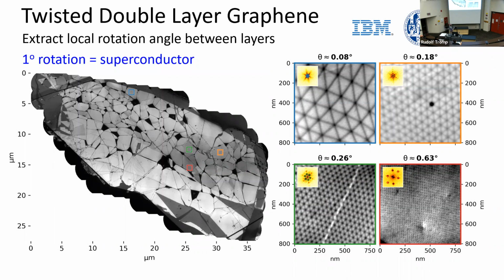By the way, they found one area where the twist angle was exactly 1 degree, brought it to a synchrotron, did angle resolved photoemission on that, and saw that indeed the electronic structure was very peculiar under that rotation.